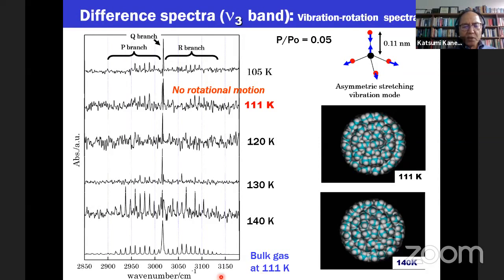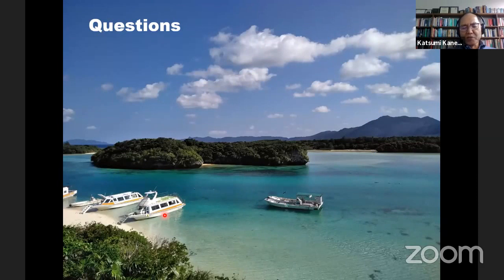In the bulk case at boiling temperature, we can observe a very nice rotational structure here. But for the confined methane around the boiling temperature, there is almost no clear rotational spectrum structure, and even at 130 kelvin, still at 140 kelvin, it is not so clear. This indicates that methane rotational motion almost stops in the highly confined state, but we can observe the central vibration peak. This means the molecules still vibrate, they don't stop, but rotations are hindered by the highly confined situation. So the adsorption states are very different.